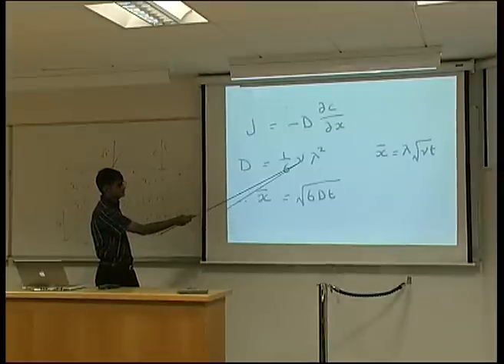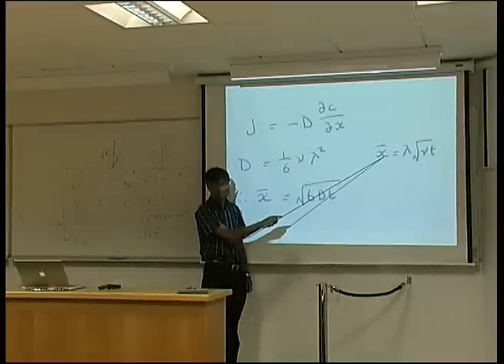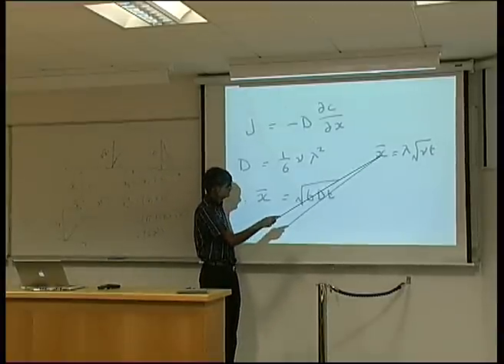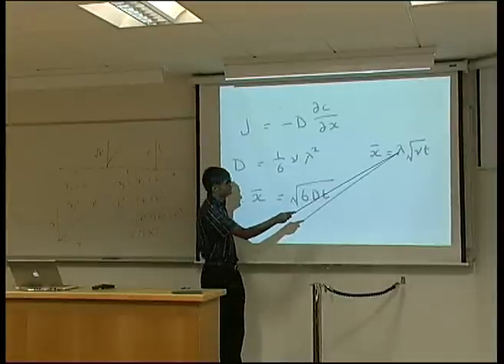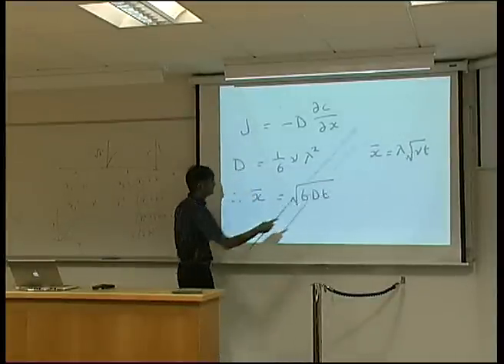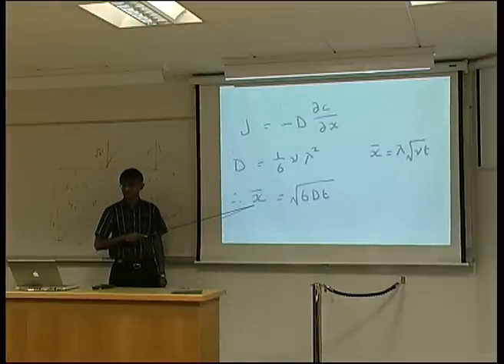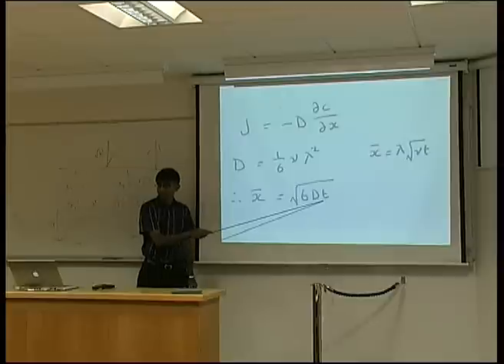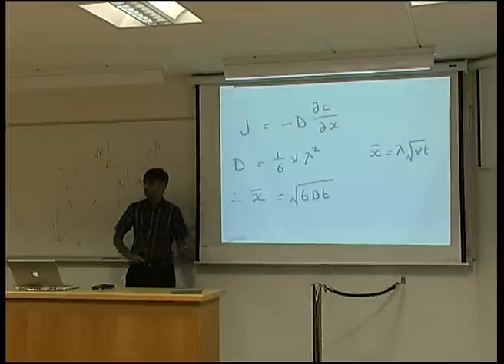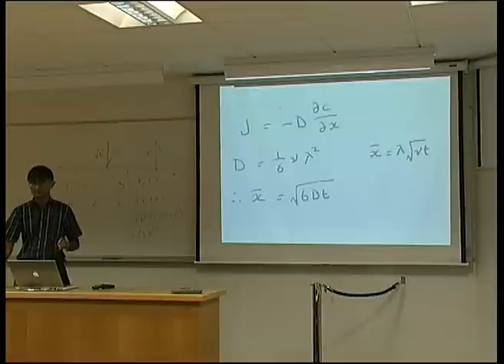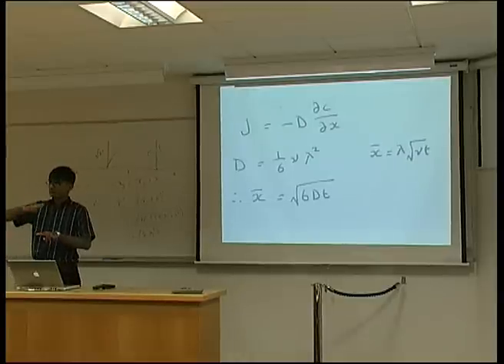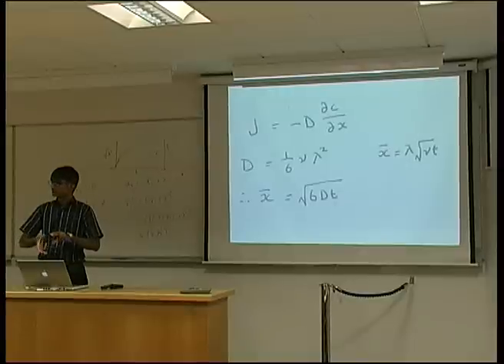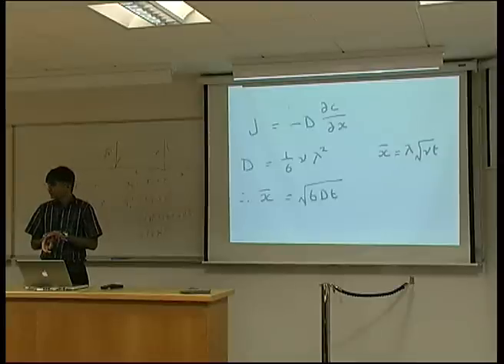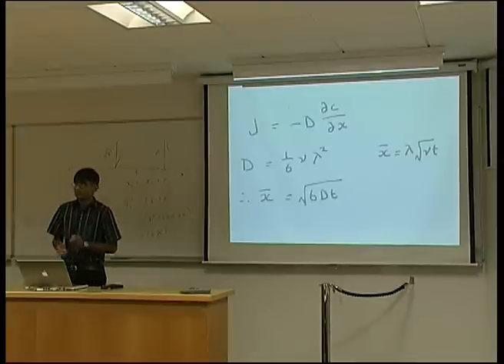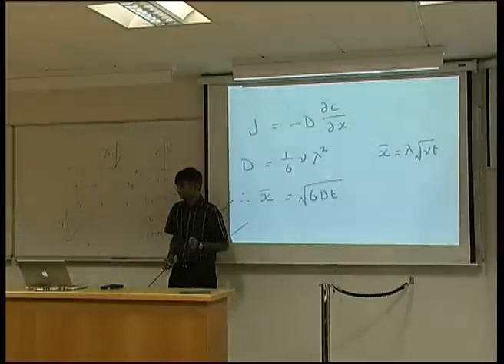Now, of course, we had this jump frequency related to the mean diffusion distance in a random walk as the step length times square root of nu t, so we can substitute for nu in here, and therefore you find that the mean diffusion distance is proportional to square root of Dt. So this is a very good way of working out a rough diffusion distance. Say you are diffusing a solute from a surface into a substrate and you want a certain depth, then you could estimate roughly the heat treatment time if you knew the diffusion distance. And again, this root Dt will appear in many equations.